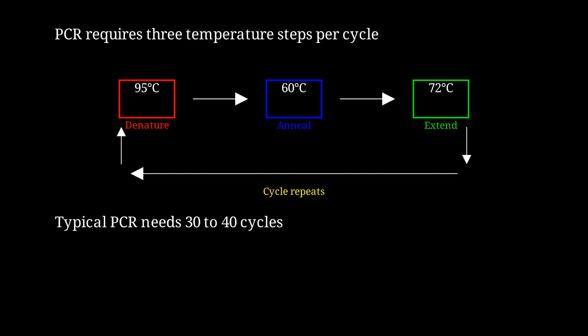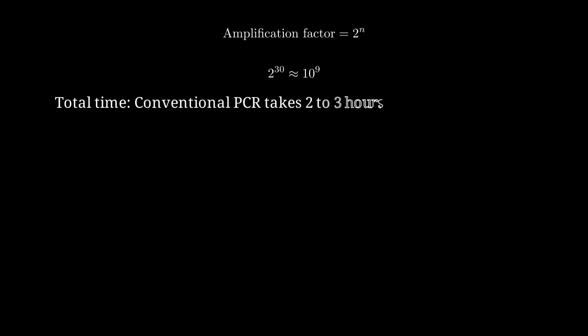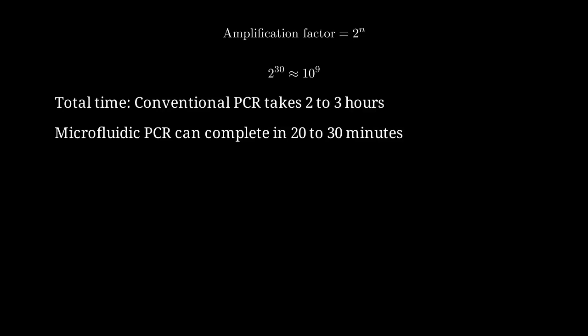Typical PCR needs 30 to 40 cycles to amplify DNA to detectable levels. The amplification factor is 2 to the power n, where n is the number of cycles. After 30 cycles, you get about 1 billion-fold amplification. This turns a few molecules into a detectable signal. Conventional PCR takes 2 to 3 hours for 40 cycles. Microfluidic PCR can complete the same process in 20 to 30 minutes due to rapid thermal cycling.